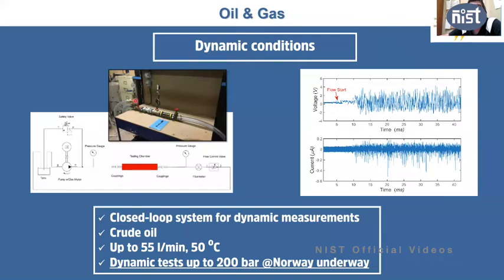So we have used oil inside, and we can go up to 50 degrees Celsius and at 55 liters per minute, but at room pressure. And now we are doing tests up to 200 bar in Norway. And this is what you get. As the flow starts here, after a little while, you get all of this output voltage coming out of your device inside crude oil in these dynamic conditions. And hopefully next week we'll have some more news on this.